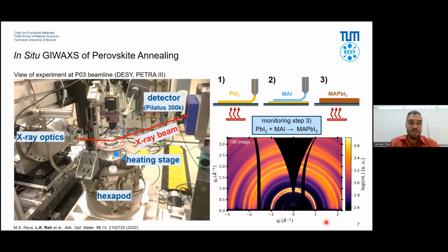of perovskite. And what is even more is that by having this GIWAXS, we can go to pole figures and go to material quantities. So we can really start with the kinetic rate equations. And in that case, we use Avrami modeling to find kind of constrained growth of the perovskite.